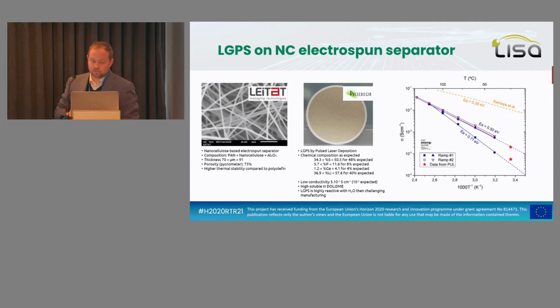The conductivity is not excellent. We get a lot of issues with this material. It is sensitive to everything, to humidity, the manufacturing, and once the cell is reacting with the electrolyte, it's really, really tricky to work with sulfide.